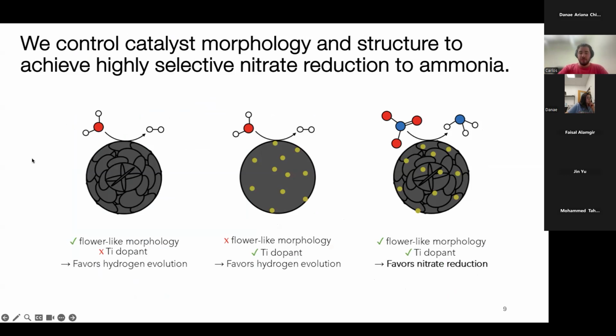So, for example, we started with carbon nanoflowers, and then we add titanium dope onto these carbon nanoflowers, and we can create titanium dope carbon nanoflowers with very similar structure. And we can also create titanium dope carbon spheres. And we're studying the differences between the activity and selectivity for this specific reaction by changing morphology and titanium doping.